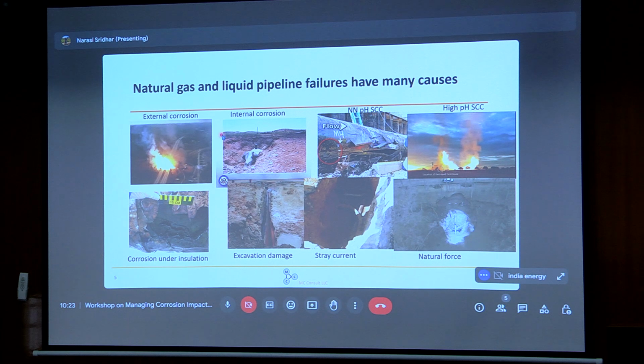Natural gas and liquid pipelines suffer from many causes that are corrosion related as well as non-corrosion related. So here is a sampling of various disasters we have had. External corrosion, this was close to where John lives in Virginia. Basically, this explosion occurred because a rock had contacted a coated pipeline, which provides a way of shielding the cathodic protection from protecting the pipeline. So this pipeline corroded in an extensive fashion, causing this burst and failure.